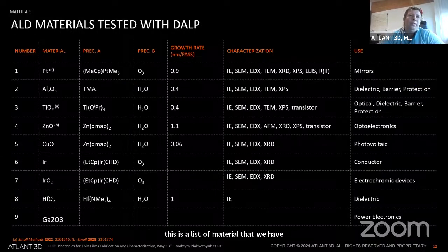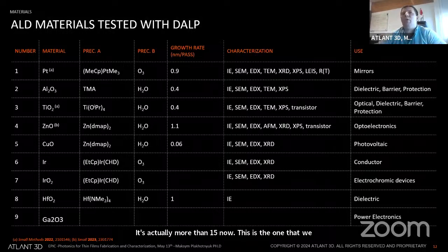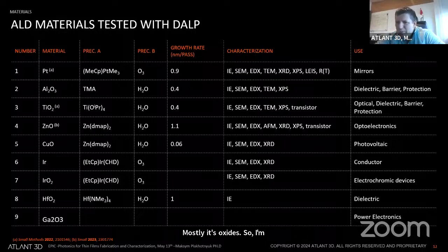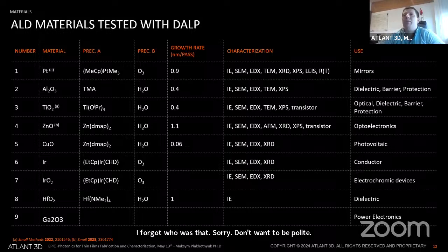So this is a list of materials that we have validated. It's actually more than 15 now. These are the ones that we have confidence we can reproduce. A lot of other materials we are still testing, so I'm not advertising them. Mostly it's oxides. IMEC mentioned, I forgot who that was, sorry, don't want to be impolite. So aluminum oxide, titanium oxide, zinc oxide, iridium, hafnium oxide. We recently demonstrated gallium oxide and are planning for niobium oxide also within the next month.